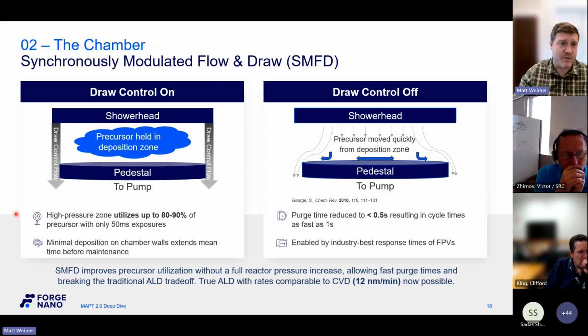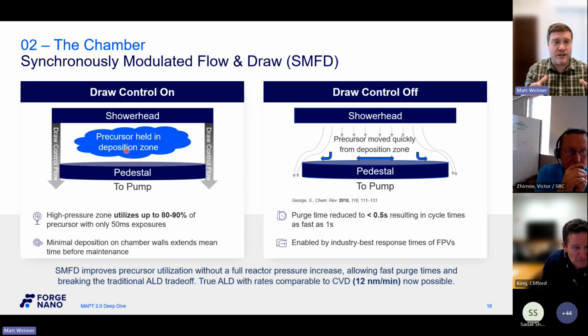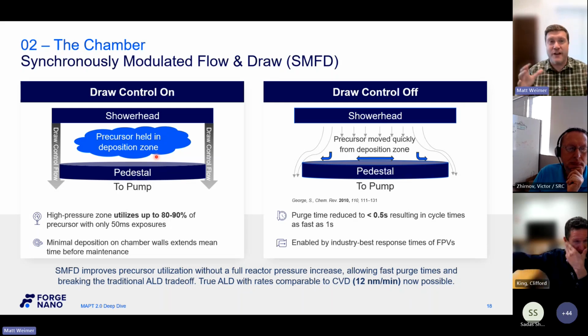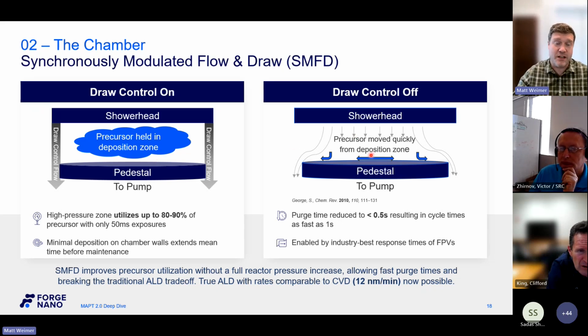When we turn this draw control on, as I'm showing on the left here, we're sort of holding precursor in the deposition zone. What we also do is artificially increase the pressure in that deposition zone. So if you remember back to my little slide earlier, this is that high pressure regime where we get to use precursor very efficiently. The other thing that's sort of hidden in here is this draw control is an inert gas, and there is some force pushing the gas back to the center of the shower head. So we get some turbulence. Now, normally turbulence in a laminar flow tool will completely kill you. You'll never be able to purge out those spaces. But because this is sort of a fake or pseudo-turbulent area, once we turn off that gas curtain, we hit our laminar flow regime just like that.